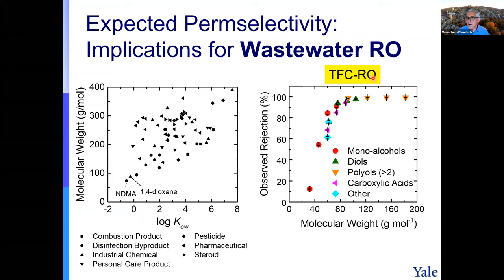TFC RO membrane. We did experiment with these solutes that I mentioned earlier, and we measured the rejection over the molecular weight, and not surprisingly, anything above roughly 100 gram per mole molecular weight, you get almost complete rejection. And anything less than 100 gram per mole, we know that it can relatively go through the membrane, especially if they are not charged.